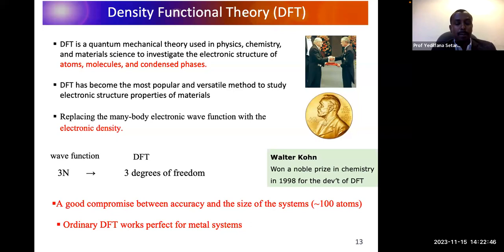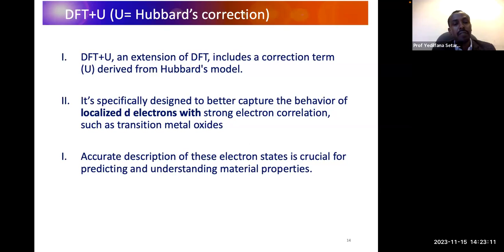However, the ordinary DFT works perfectly only for metals. But as I said before, unfortunately, the battery materials, especially the cathodes, are insulators and they are nonmetals. So ordinary DFT may not perfectly describe the properties of our materials. So instead, we have been using DFT plus U. This is an extension of DFT that includes the correction term U, derived from the Hubbard model mathematical expression. It is specifically designed to better capture the behavior of the localized d electrons with strong electron correlation, for example, in the transition metal oxides.